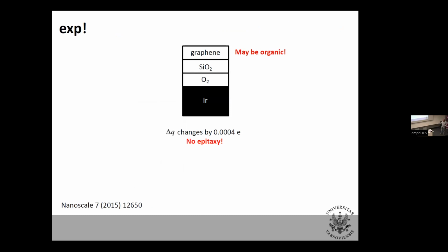In our case, the effects are 3 orders of magnitude higher in our theoretical experiment. So you realize this, and we added this, of course, to the paper and said, look, we think one precedent is already known, but basically there is a huge room for improvement, 3 orders of magnitude.